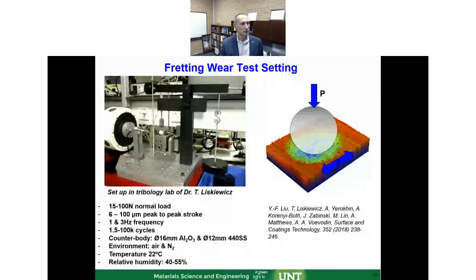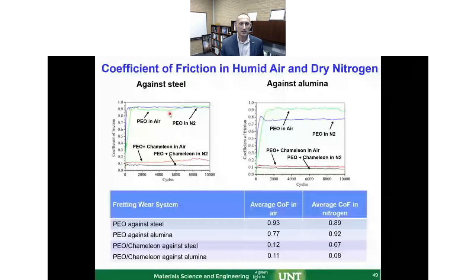I just want to make sure to mention that yes, the stick-slip transition was also drastically reduced for this chameleon composition. But on gross slip, if we have the plasma electrolytic oxidation coating without any chameleon, the friction coefficient is high, as expected; it is a hard ceramic.